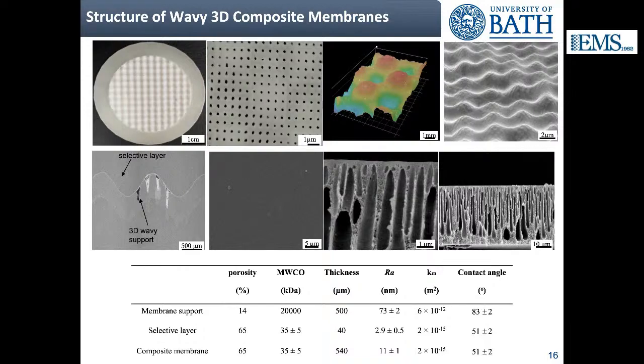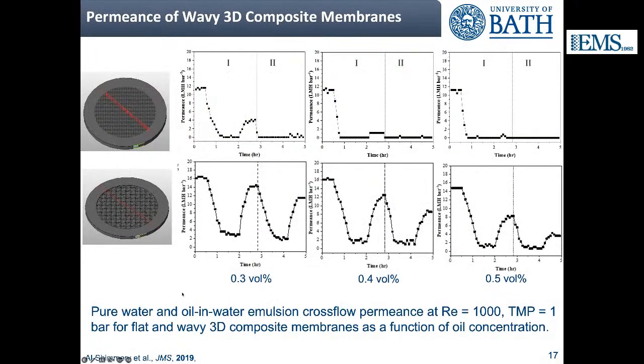And in terms of performance, you can see that the composite membrane takes some of its characteristics from the selective layer, like the porosity, the molecular weight cutoff, and the contact angle. But then the roughness is an average of the selective layer and the membrane support. So let me show you now some results.